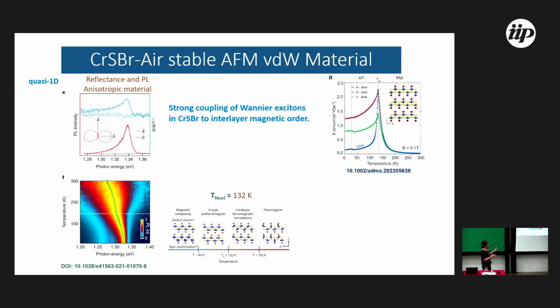So this material is very special. I will explain why this occurs, but the exciton is coupled with the magnetic order, and you have magnons coupled with excitons, and polaritons coupled with magnetic properties. These are really special properties that you cannot find in other materials. I forgot to mention that it's an antiferromagnetic material, A-type, and the Néel temperature is 132 K for bulk material. If you exfoliate and have few layers, the Néel temperature decreases.